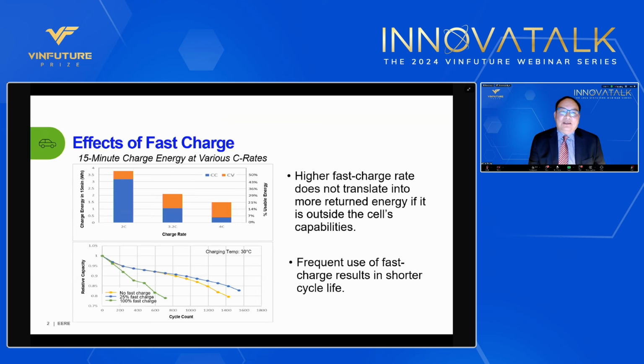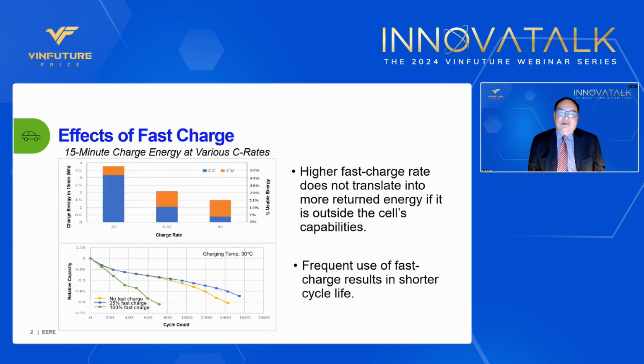So today we talk about the fast charge. In general, the typical charging protocol is a constant current and then a constant voltage. Basically, when you hit the upper voltage limit, you begin to do constant voltage charging. So you look at the chart here, the plot here, especially the top plot. What we try to do is take 3 cells, they're all identical cells, and try to figure out how much charge you can charge them up in 15 minutes at different rates. So typically a C rate means an hour, 2C rate means half an hour of charging, and so on.